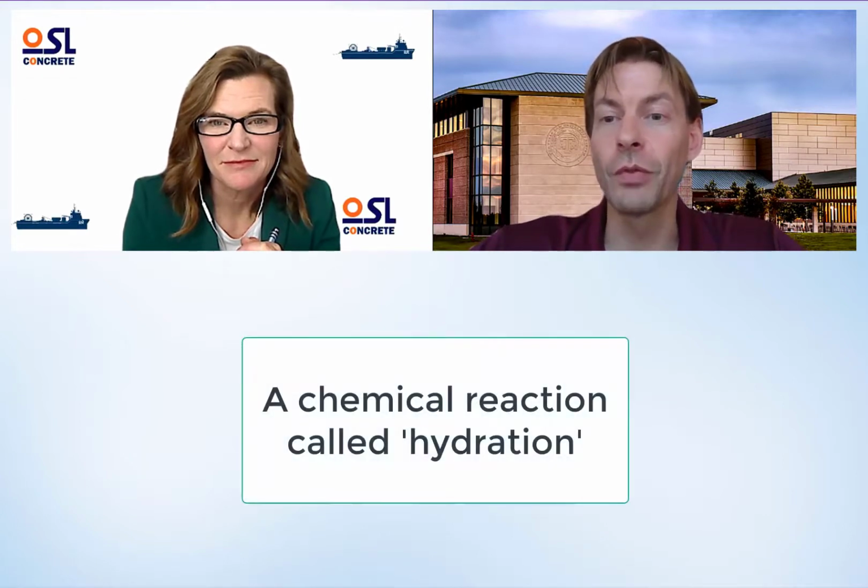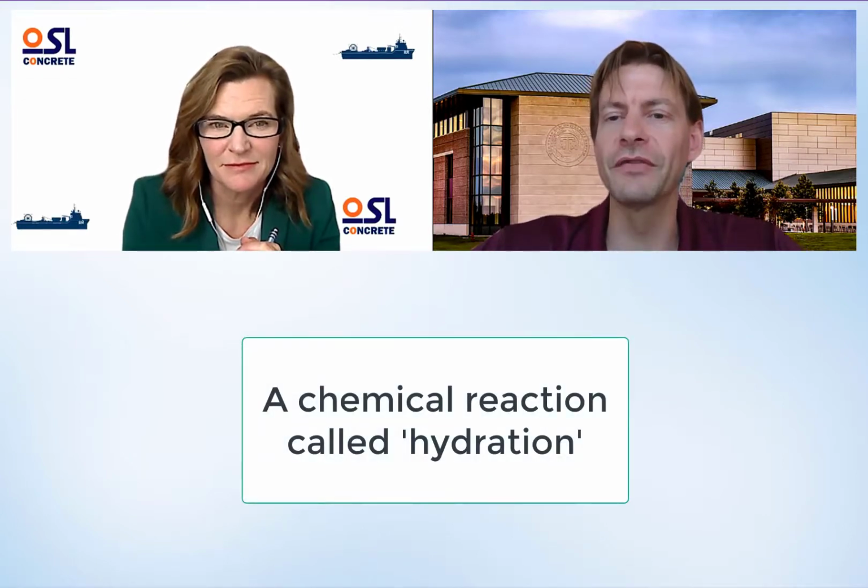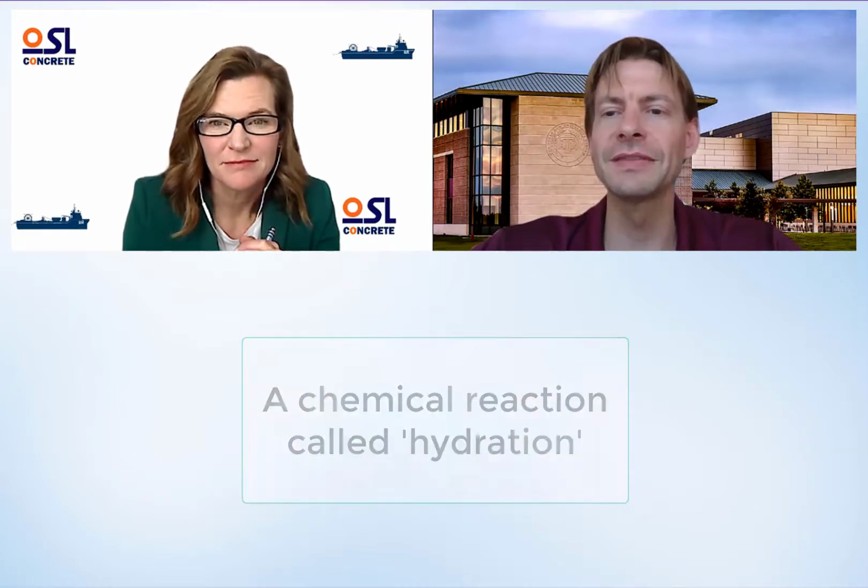Yeah, if you didn't have cement, you just have muddy water, okay, with a little bit of sand and gravel, crushed rock mixed in. Cement is the magic powder. Cement chemically reacts with water to form these different solid products. Calcium silicate hydrate is the main one, that essentially glues together all of the sand and the rock to make a hardened mass that has the properties of interest to us as engineers, right? It gives us the strength, the durability, the thermal properties. All of these characteristics we need depend on there being cement, this chemical reaction between cement and water. So you can't totally get rid of the cement.